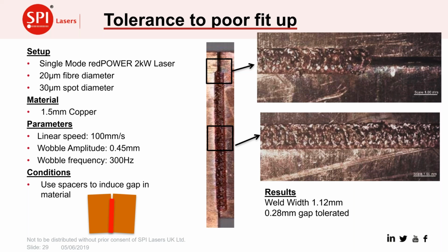So we set up a weld with about 0.45 millimeters for the wobble amplitude, which was obviously giving us a 0.9 diameter, and then the weld was just slightly wider than that, at just over 1 millimeter wide. So we're able to weld very cleanly, no spatter, through copper, even though there's a deliberately introduced gap in it.